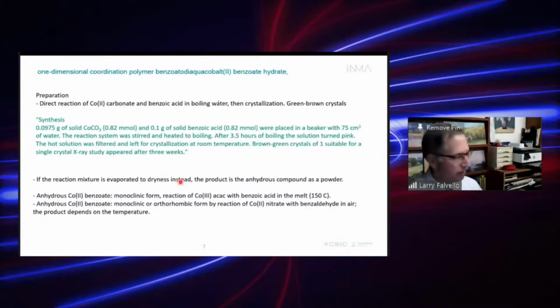So cobalt benzoate has been around a while. It was first prepared, as far as I know, in 1925. And there are several hydrates. The one we characterized is a trihydrate in the sense that it's got 2 aqua ligands and 1 free water, one unique free water in the crystal structure. The synthesis is just boiling the components in water, cobalt carbonate with solid benzoic acid. And then you let it sit for 3 weeks or so and you get crystals.